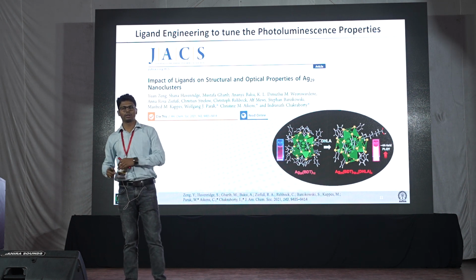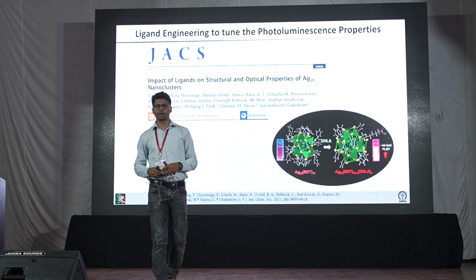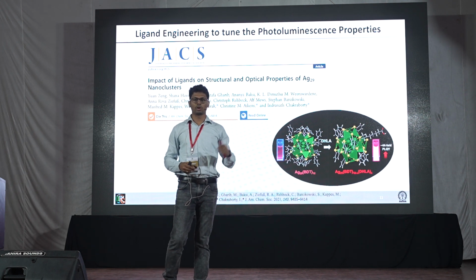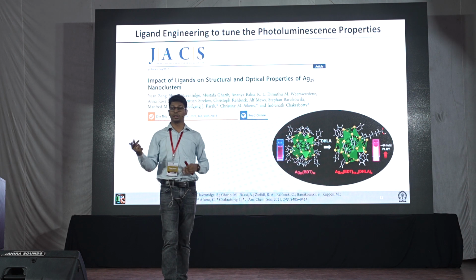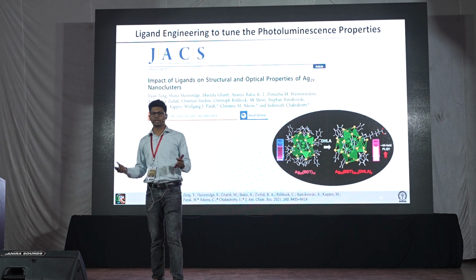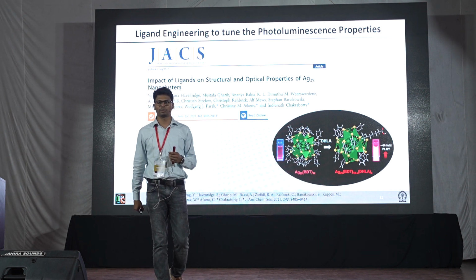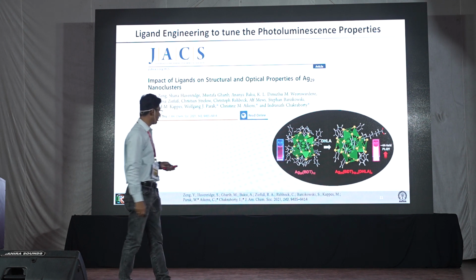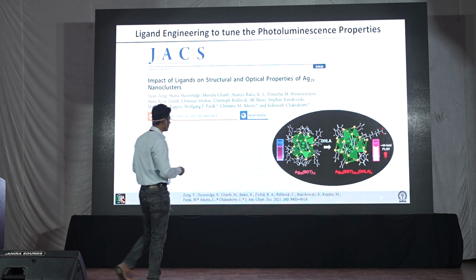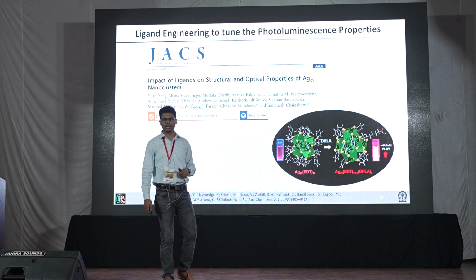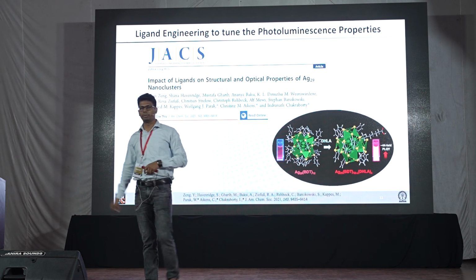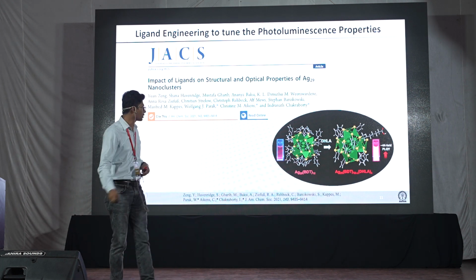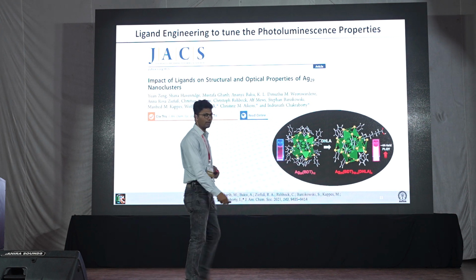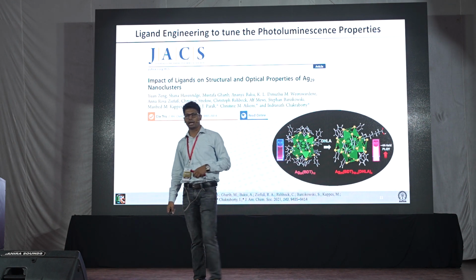And if we go back to the series of clusters reported so far, most of the water-soluble clusters have a high photoluminescence quantum yield. So what was the reason that could lead us to the mechanism? That is why we dug into this particular problem. And what we found is that if we exchange the ligand on Ag29 BDT with DHLA, it enhances tremendously. The photoluminescence quantum yield goes up almost 44 times.